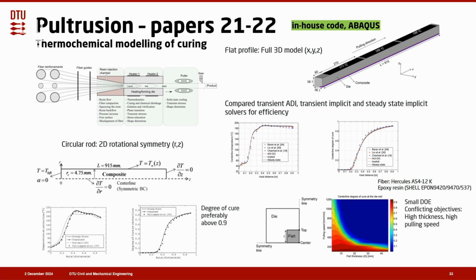And then we did a small DOE where we looked at how fast can you actually pultrude a part if you want to make it as thick as possible, but pull as fast as possible. And pulling fast, of course, increases productivity. But if you pull fast, it doesn't have sufficient time for curing. So, of course, these are conflicting objectives, and then we made this, you could say, optimization curve.